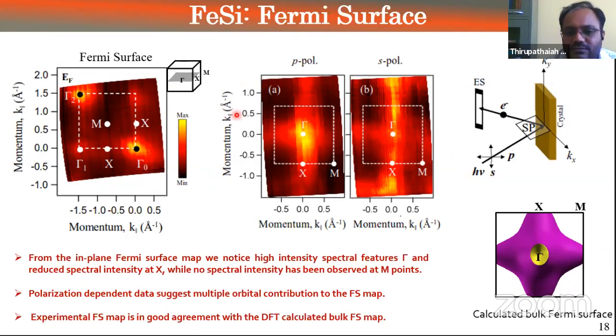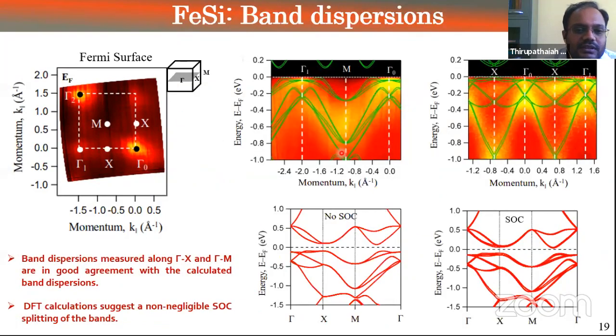Okay, and then the data whatever we collected was in pretty good agreement with the calculations. So this is the Fermi surface map for the bulk, which is in good agreement with the experimental Fermi surface map. And then we made band dispersions along, I think, this one is along gamma to M, this direction, and this one was this direction. As you can see, we also overlapped the spin-orbit coupled band structure on top of it, which matches very well. So the experimentally obtained band structure matches perfectly with the calculated band structure, and it's the same in both cases.